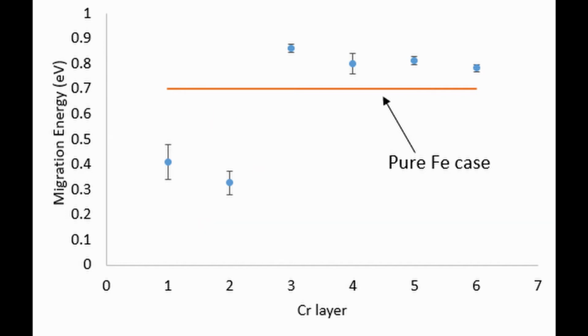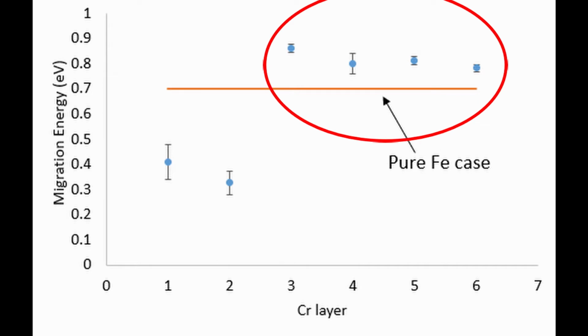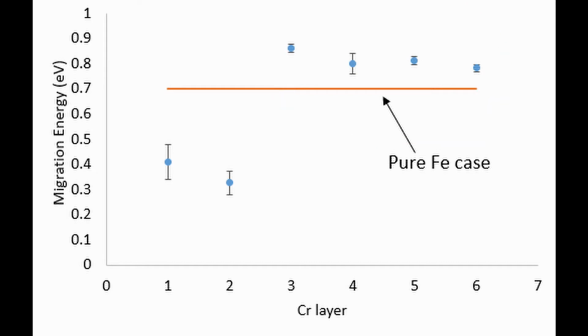After the first two layers, we noticed that having chromium in the structure increased the migration energy to higher than that of the pure iron case. We would expect that if deeper layers were tested, the values would eventually converge to the pure case. This indicates that having chromium in the surface increases mobility, but chromium in the bulk structure decreases mobility.